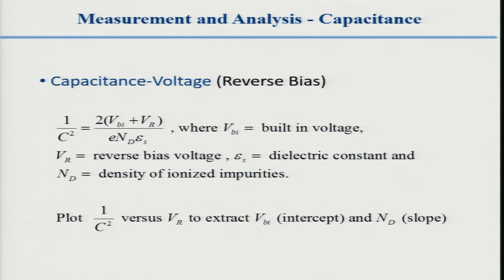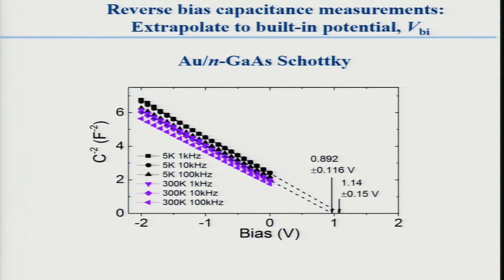So we can measure the built-in potential when this is a nice linear plot, the 1 over C squared plot. V is a reverse bias. This is the dielectric constant, which we know. And N sub d is a donor density of ionized impurities. You can, with different wafers, have different impurity densities. So you plot 1 over C squared versus V_R to get an intercept and a slope, which gives you the carrier, the impurity density. And these are our typical plots.